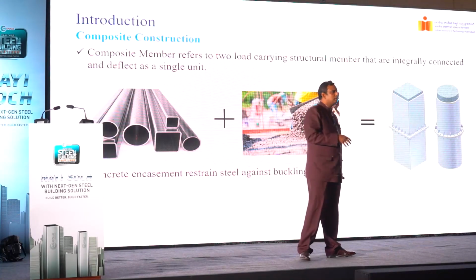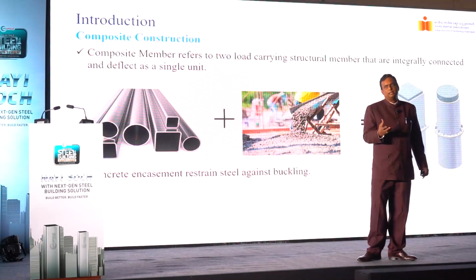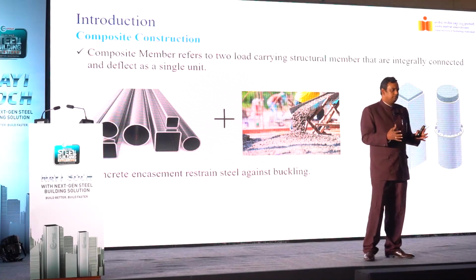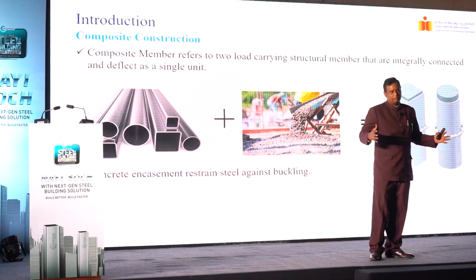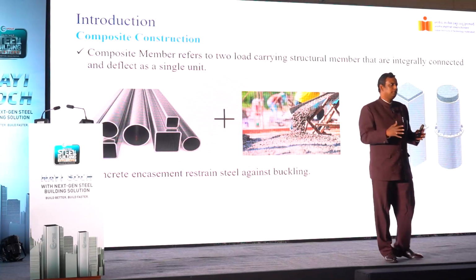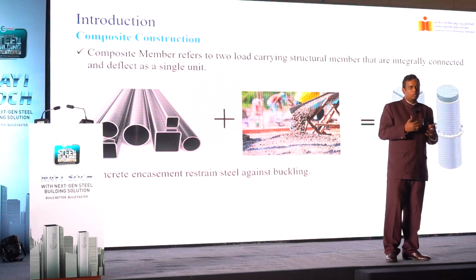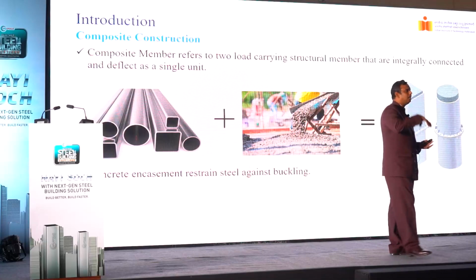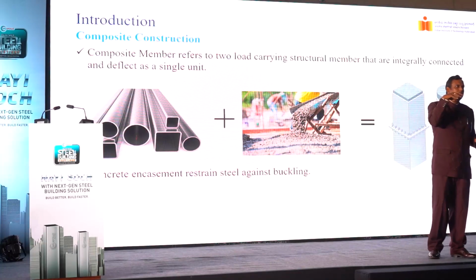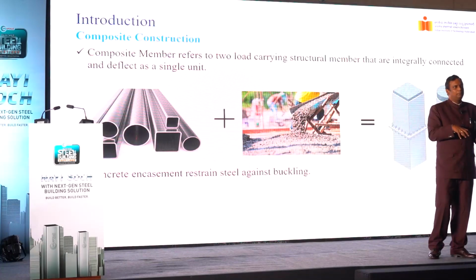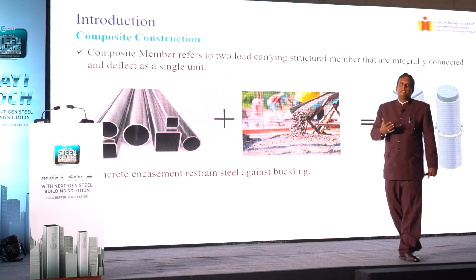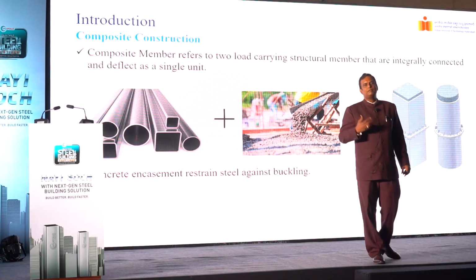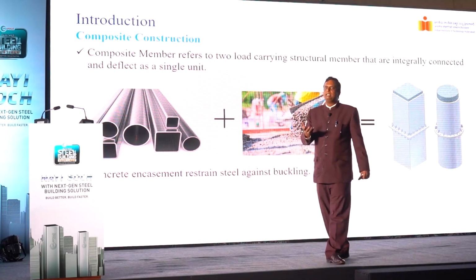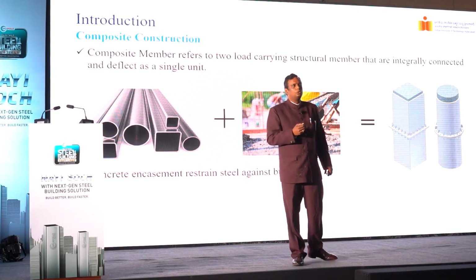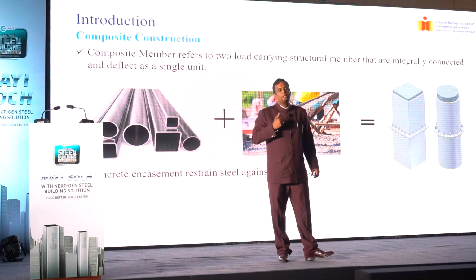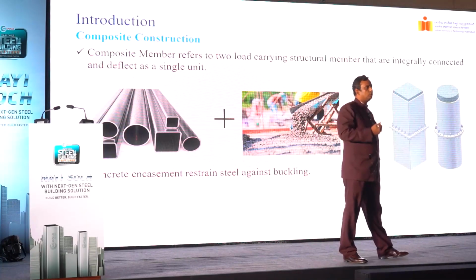The major reason that we have concrete in it is simply to prevent what is known as local buckling. You want to reduce the quantity of steel and make the sizes bigger. But if you don't put something in it, there is a possibility that it could buckle inwards, which we call local buckling. So in order to prevent local buckling, if you add a material, which is concrete, for example, it will add strength, but at the same time it will prevent the formation of local buckling, which is an undesirable failure mode. What we need to achieve is the complete ultimate load capacity. Local buckling is one such phenomenon that will erode the strength. So the good thing is that we reduce local buckling.